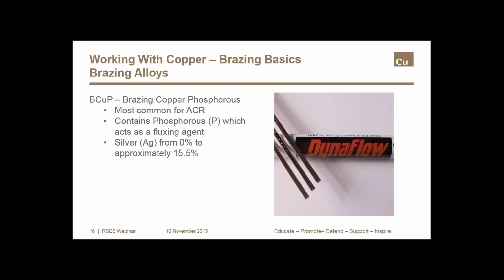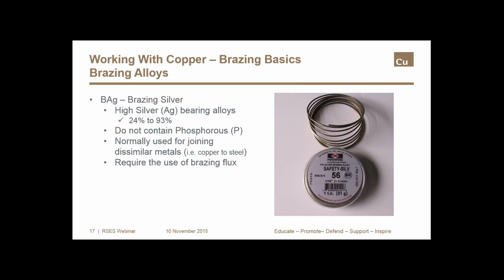Looking at the composition of BCuP filler alloys, there's phosphorus in amounts that vary from about 4 to 7.5%. The phosphorus in this alloy acts as a fluxing agent. So, when joining copper to copper using a BCuP brazing filler, there is no need for a separate fluxing operation. The filler metals that contain silver, the BAg series, are used to join dissimilar metals. These brazing fillers can contain a considerable amount of silver, making them rather expensive in comparison to the BCuP fillers. Note that the BAg fillers do not contain phosphorus or any other metal that would act as a fluxing agent. Therefore, a separate fluxing operation is required when you're working with BAg brazing fillers.